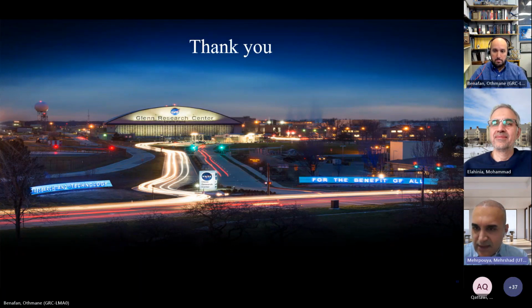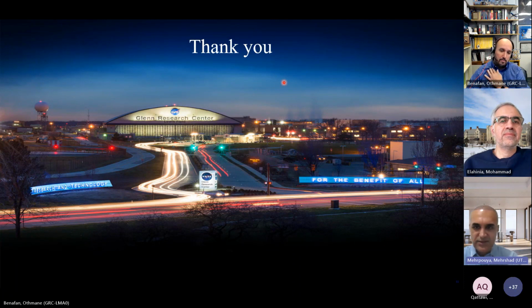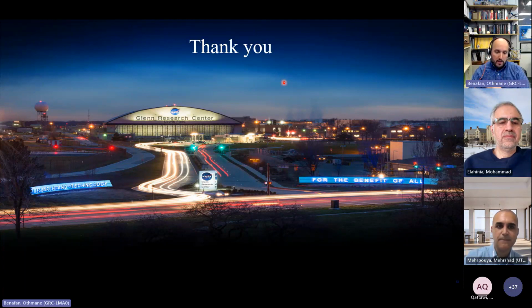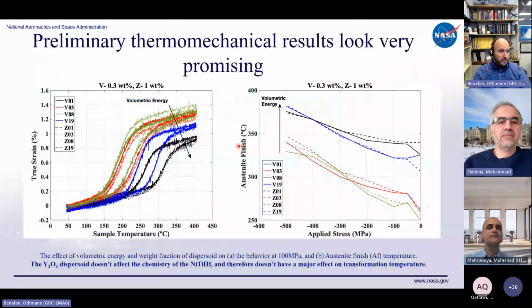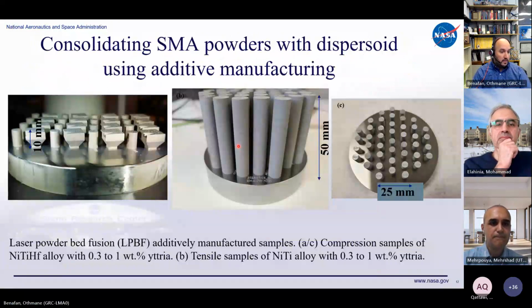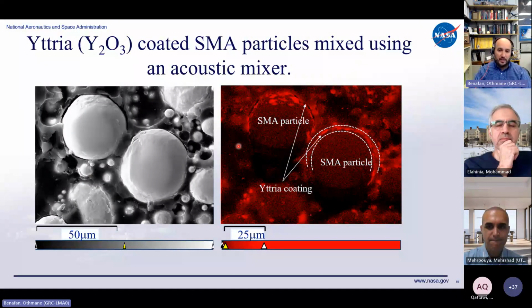Anwar asks, is there any way to confirm, as shown in slide 10, that the coating you apply for the SMA is consistent throughout all of the alloy elements in the SMA? So, it's not segregated. Let me see, slide 10 you said? Yeah, there isn't necessarily a segregation if you use the right mixing protocol. The majority of the particles are coated in a similar way, and we have bigger maps of this blown up throughout, and you can see that most powders are coated the same way. So we can achieve uniform coating.